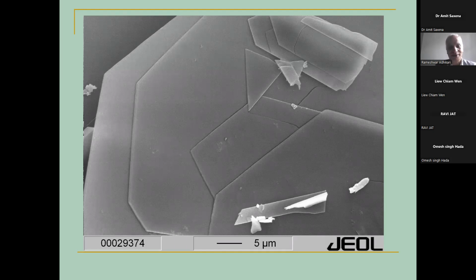There is a reason. In a simplified way, when you go from one uniform plane to another plane, at the edge, in the boundaries, you have the area where the electron beam is falling. You have here a kind of spherical interaction volume, and here a kind of elliptical scattering volume. It takes more volume to interact with the specimen surface. That produces more secondary electrons, and that makes the regions appear brighter. This is a very general picture. There are many other factors too. If we know this information, then we can better interpret scanning electron micrographs.